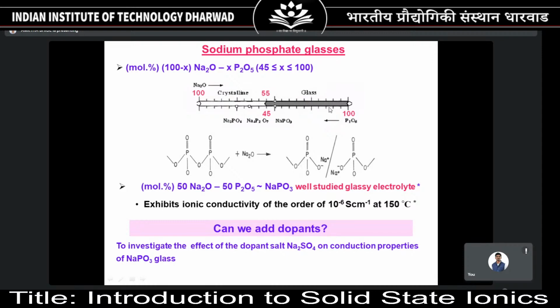See, this is the glass. Beyond that, you won't get any glass. It can be a mixture, it can be a crystalline material. You cannot have glass properties. Glass properties are limited only to this composition: between 45 and 100 minus 45, that is 55 mole percent of sodium oxide, and 45% of P2O5 will give you the glass, and you have a wide range of composition.